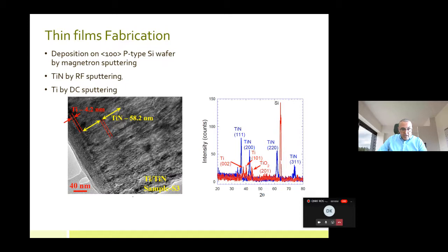Here, what you see is a TEM image that was taken here in Qatar. You can see a titanium layer, which is about 4.2 nanometers, and then a titanium nitride layer, which is about 60 nanometers. So we're able to achieve these alternating layers, but the question was, can we control it? Another thing, if you look at these glancing angles, you can sort of confirm that these are indeed titanium and titanium nitride, so we had some confidence.